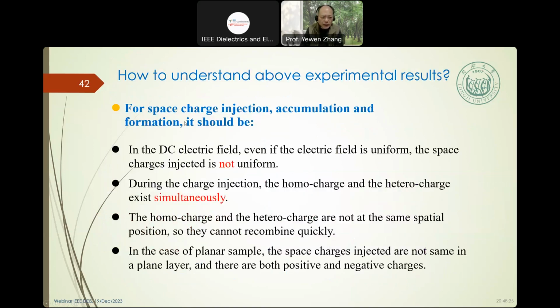So we get the simulation. For the spatial charge injection, accumulation and transport under DC voltage, even if the electrical field is uniform, the space charge is not uniform. During the charge injection, the homo charge and hetero charge occur simultaneously. So there is a space charge, including sometimes the homo charge and the hetero charge, meaning positive or negative. The homo charge and the hetero charge are not in the same spatial position, so they cannot recombine quickly. In the case of a planar sample, the space charge injection is not in the same layer, so there are both positive and negative charges.